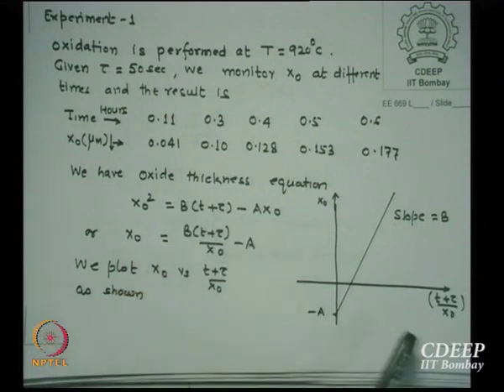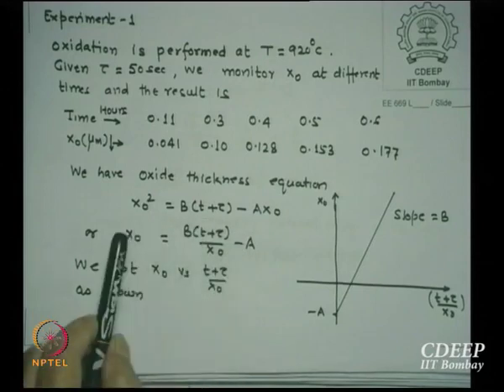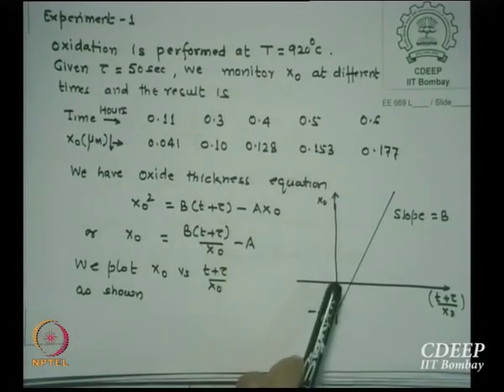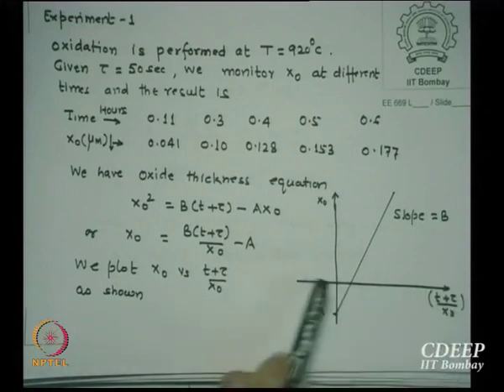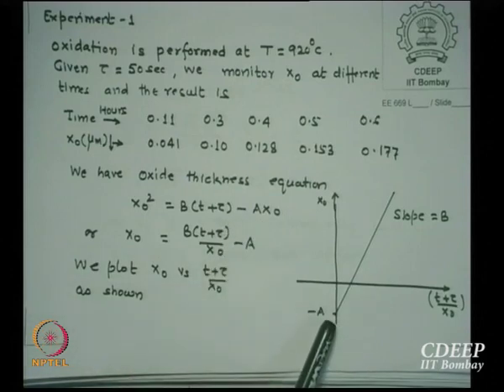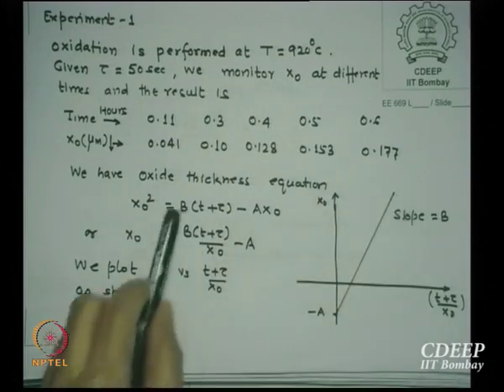Since x0 square is B(t plus tau) minus A x0, I get x0 is B(t plus tau) by x0 minus A. What does this equation look like? This is a y equal to mx plus c kind of equation, linear. So if I plot (t plus tau) by x0 versus x0, somewhere at 0, that is t plus tau by x0, at this point, whatever is the constant is minus A. So you can monitor that minus A. In actual, I just want to make it parabolic, I said neglect A, but in calculation I will take care, because I need to know A. So by extrapolating this curve, I will get minus A, and the slope is B.